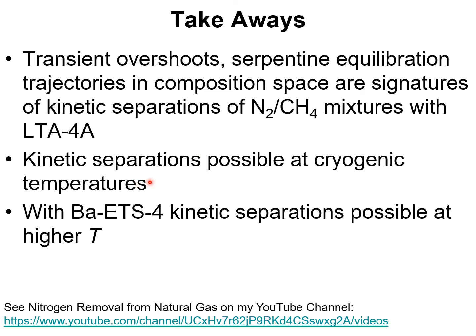On the basis of breakthroughs in fixed bed adsorbers, we've also established that kinetic separations with LTA 4A are only possible at cryogenic temperatures. As the temperatures are increased to above, say, 270 or 280 Kelvin, no kinetic separations are possible.